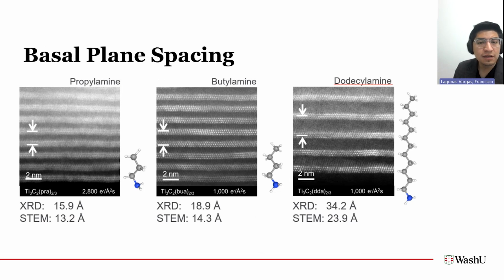And if we measure this basal plane spacing for these different MXenes, we start seeing that maybe things are not as we thought. So if you see on the bottom here, we compared our STEM measurements of this basal plane spacing with those from X-ray diffraction. And you can see that STEM consistently gives us smaller spacings compared to XRD. So even though we didn't expect to see any changes, or we thought we had found the appropriate dose threshold for these materials, it's clear that something is already happening.